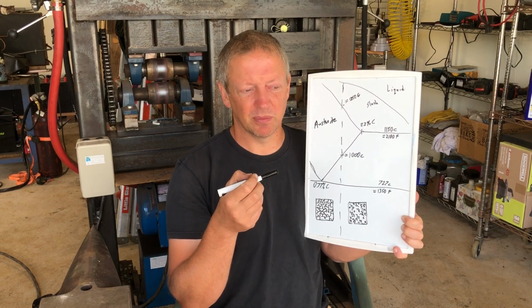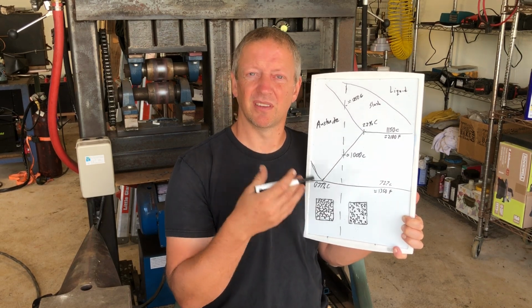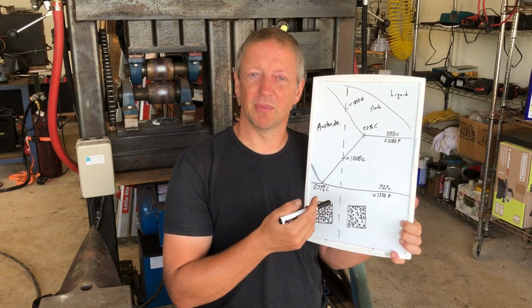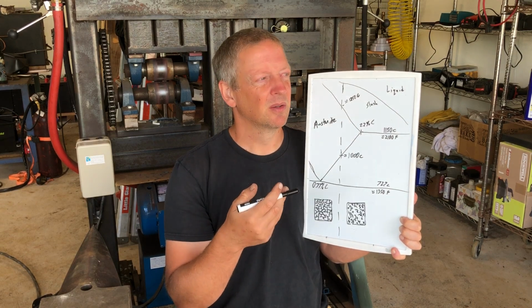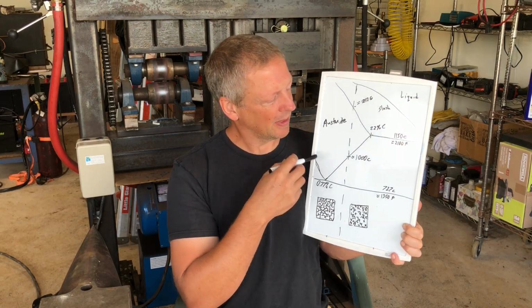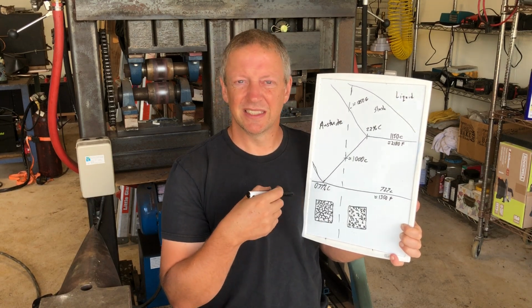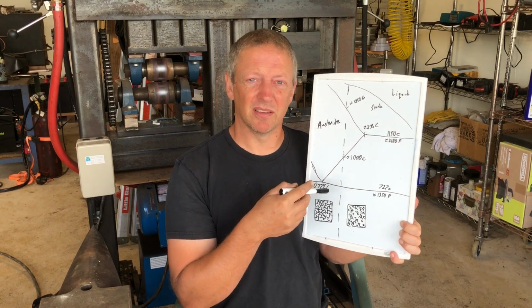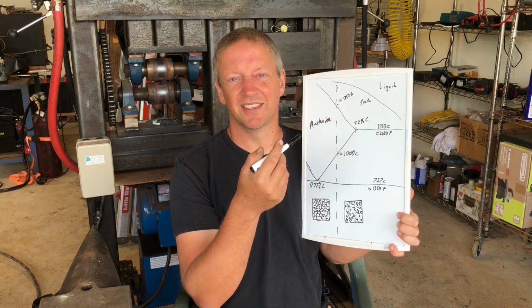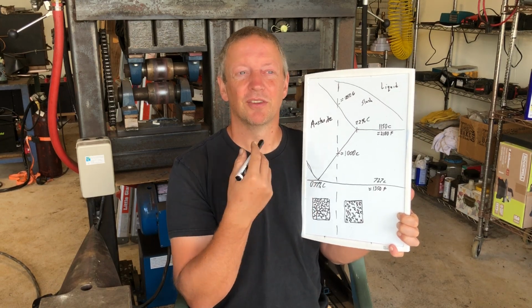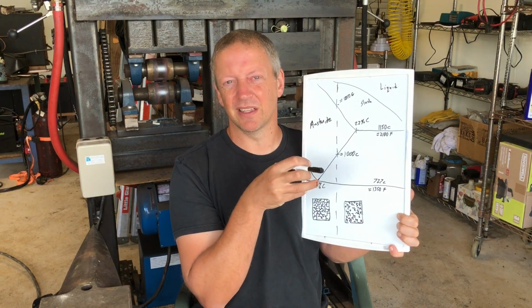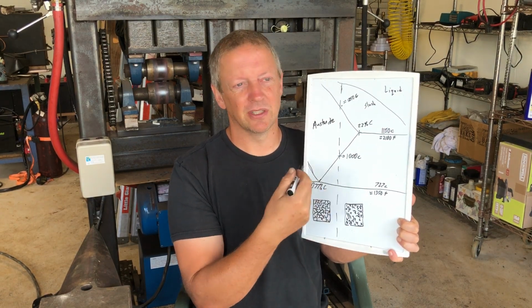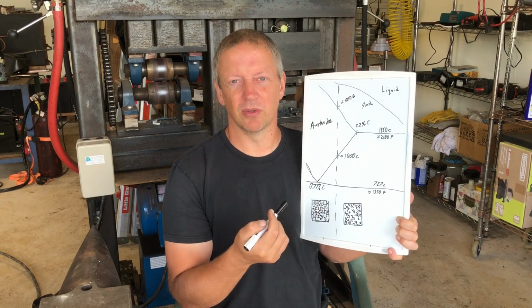Another common place is if you have carbide forming elements. They bond more strongly with the carbon, so they are more likely to precipitate carbides. And lastly, carbides make really good precipitation points for more carbide, because again, they don't fit nicely into the crystalline lattice, so you get dislocations around those carbides.